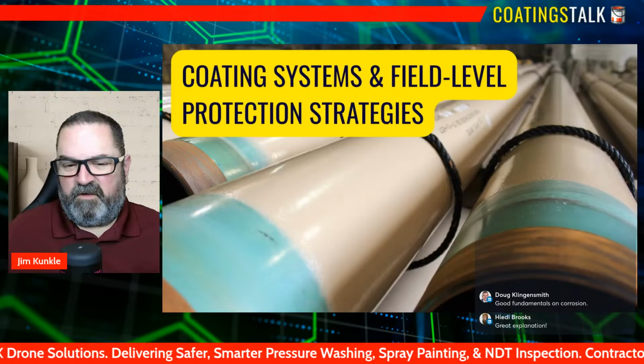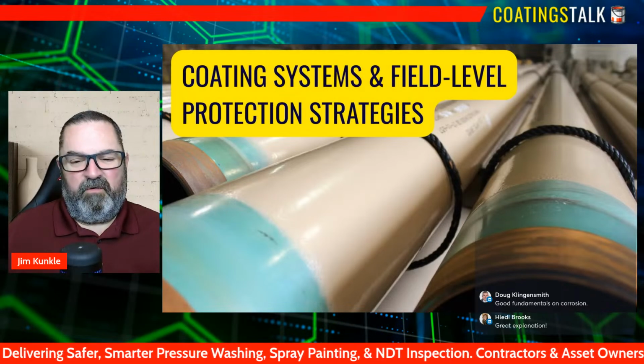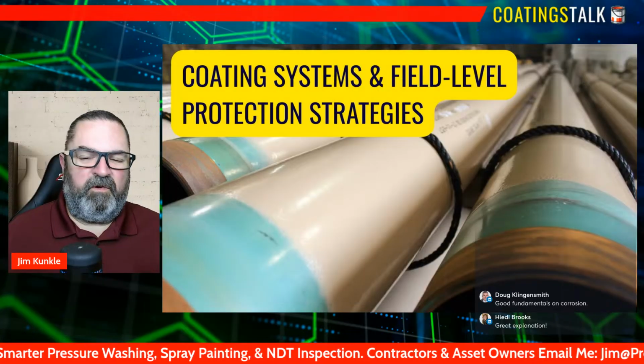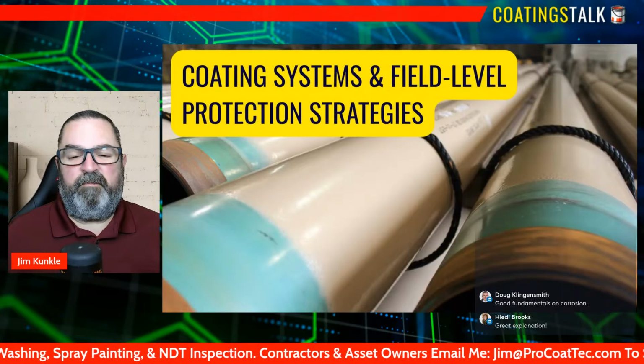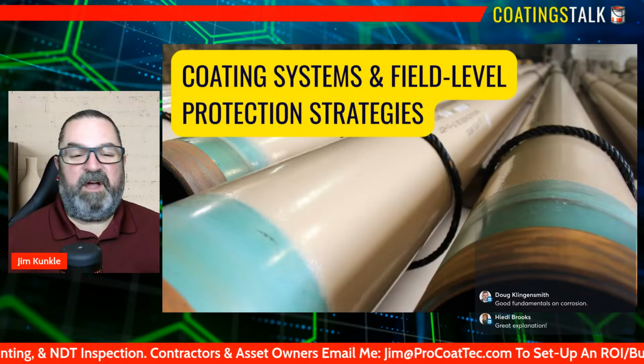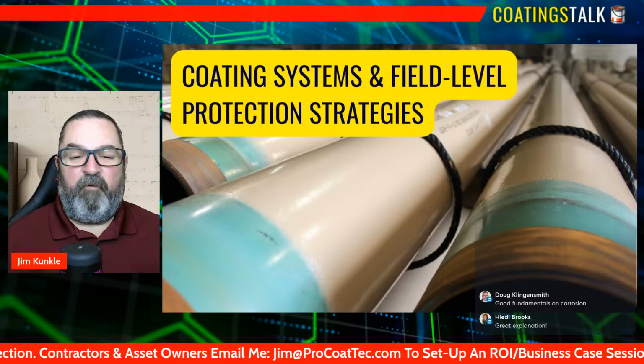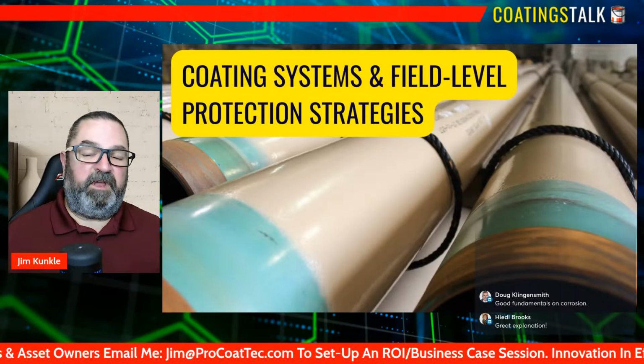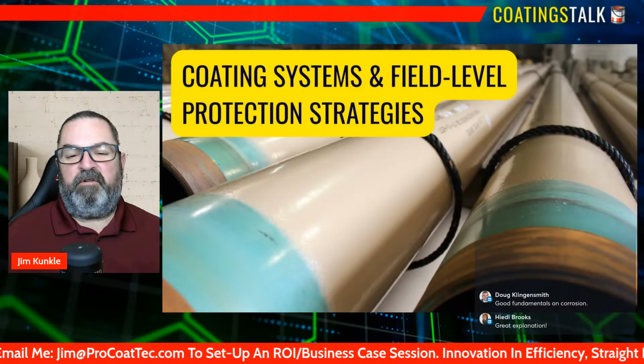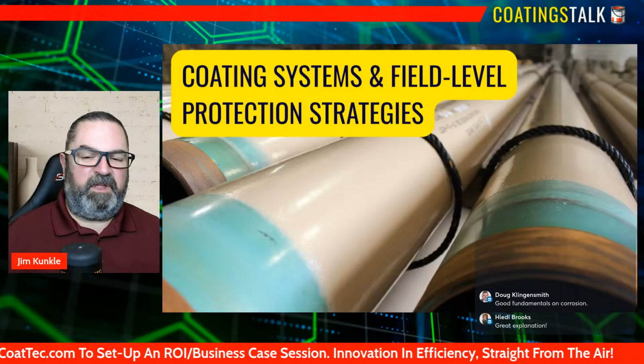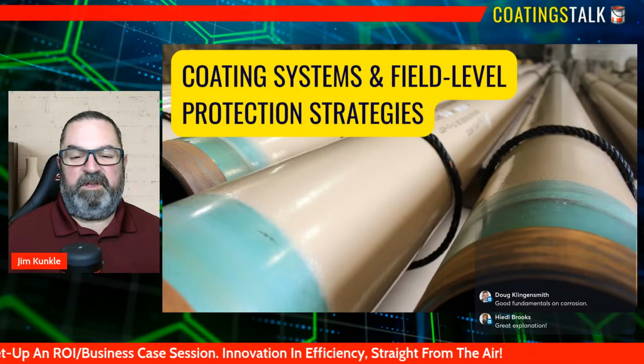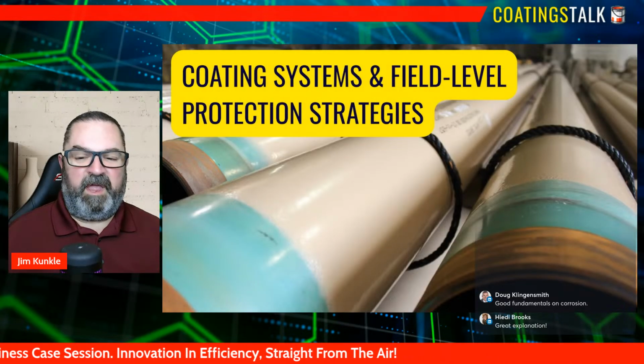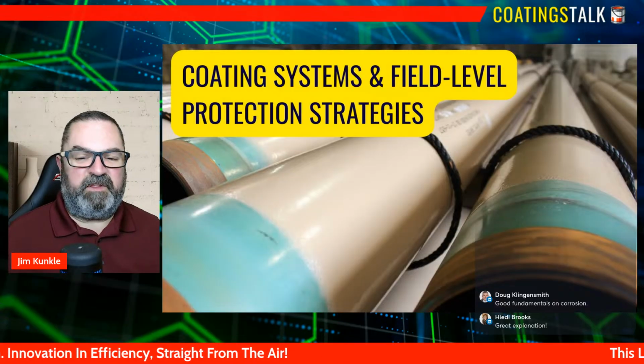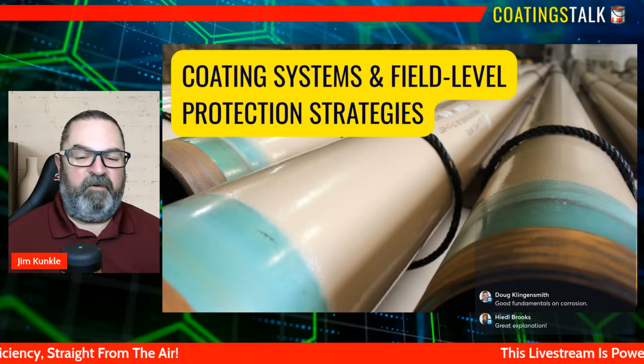Even simple oversights like failing to stripe coat high-risk areas or neglecting to clean equipment between coats can compromise the entire system. Avoiding these mistakes starts with discipline and awareness. Field teams should follow surface preparation standards rigorously, verify environmental conditions before and during the application, and use calibrated gauges to confirm film thickness.